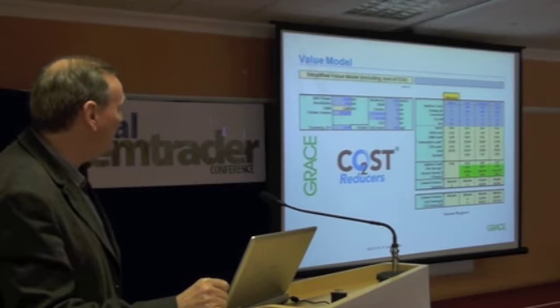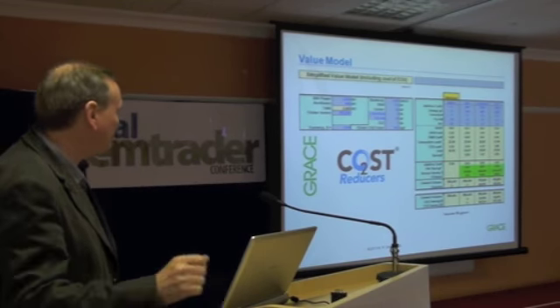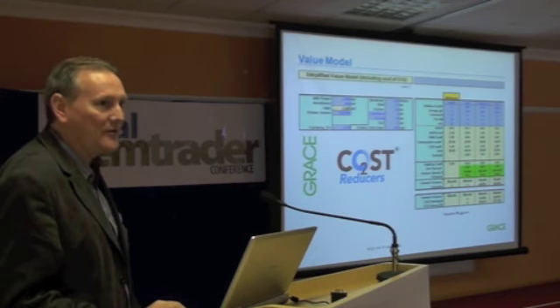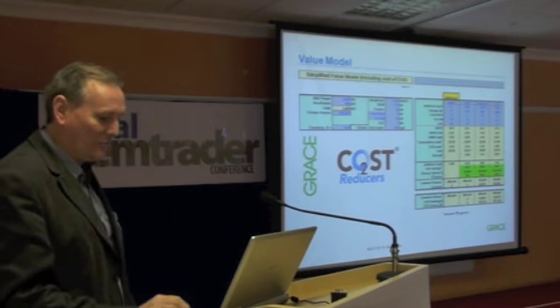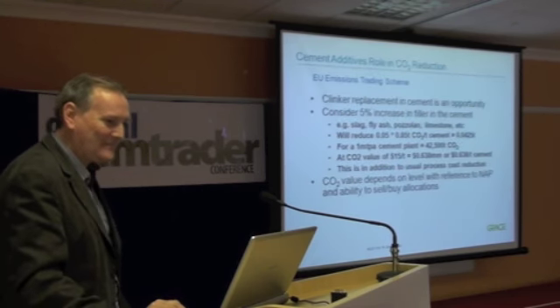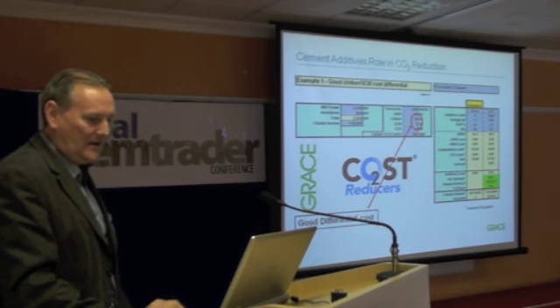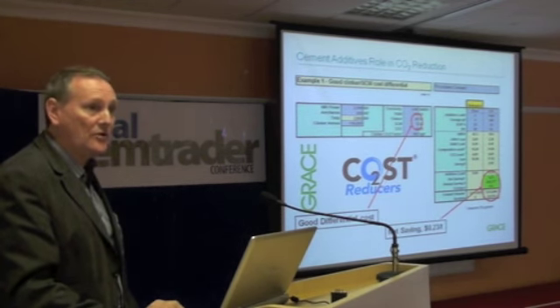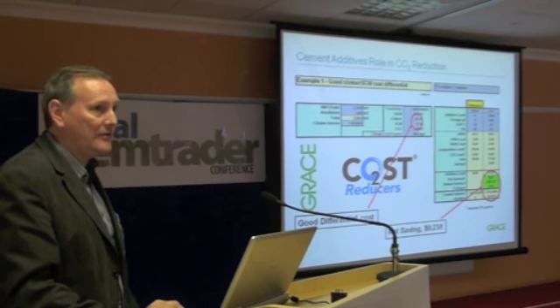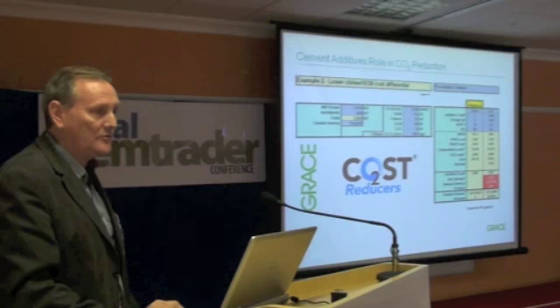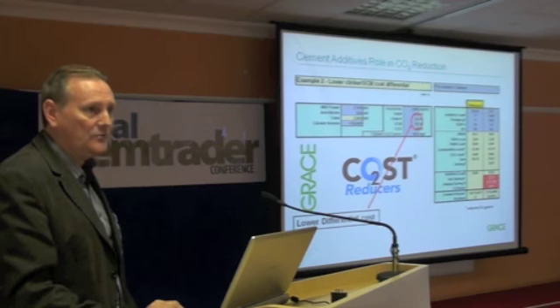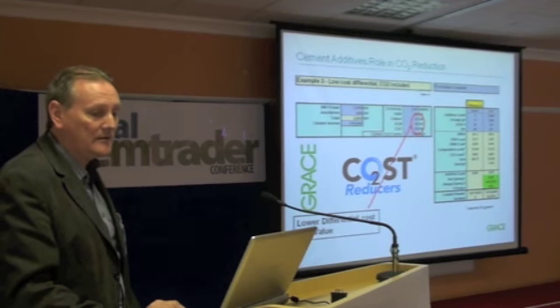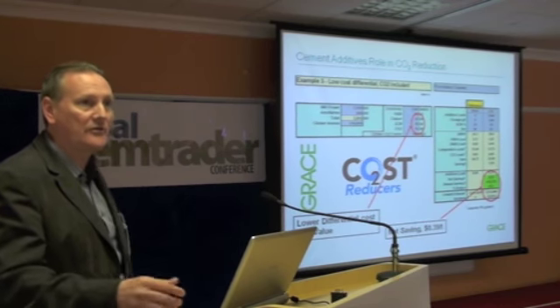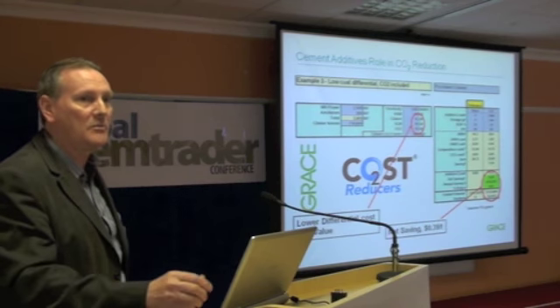And here we're only using CO2 at 7 euros per tonne. And there's a lot of debate about the value of CO2 and where that might go. Definitely a topic for another conference. It's sometimes true that when you've got a big differential cost, then you can make savings using additives without taking into account CO2. But we do have cases where the differential cost is less and we can't justify the use of a chemical additive. But if you bring the CO2 into the equation, then you can make a difference. And this was the basis of some of the CDMs that took place where you can apply for credits.